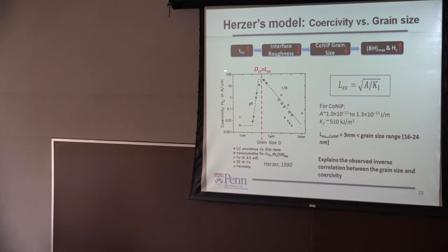So now you know the chain reaction, right? The increase of the copper layer will reduce the interface roughness and further reduce the cobalt nickel phosphorus grain size, and finally influence the properties, especially the coercivity and BH max.